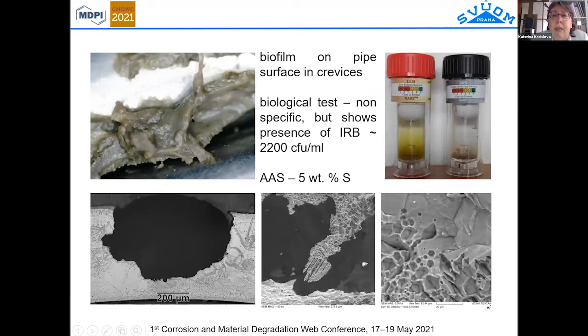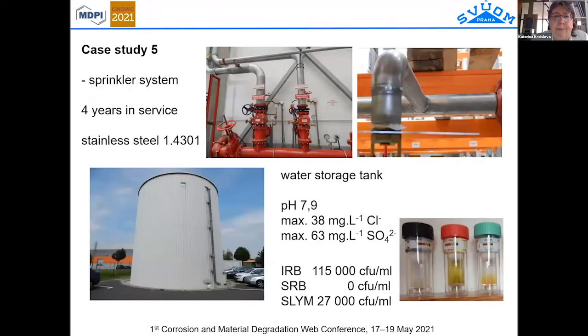This biofilm we tested for the presence of some bacteria. It was not very successful, but it shows some existence of, again, iron reducing bacteria. The characteristic pits and the morphology of the residue were again typical for microbiologically induced corrosion, and the content of the sulfur was relatively high.